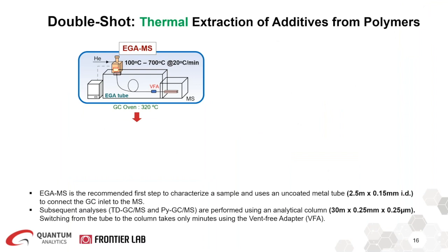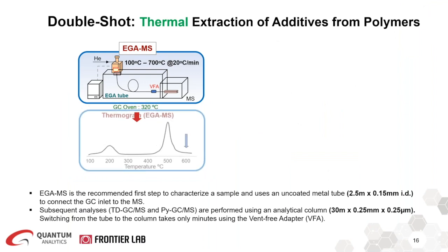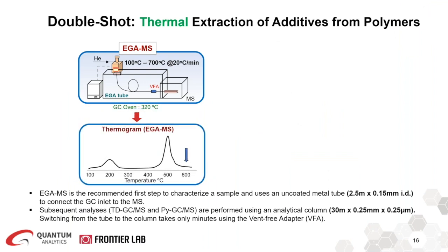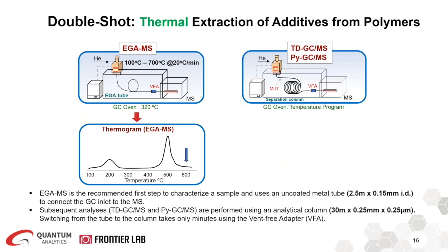This is the double shot analysis, which is the thermal extraction of additives and volatiles from the polymer. So first, the EGA is performed. In this case, 100 to 700 C, 20 degrees per minute, and as shown here, the EGA thermogram is obtained. To further analyze the peaks from the EGA, the tube is switched to the separation column using the vent-free GCMS adapter.